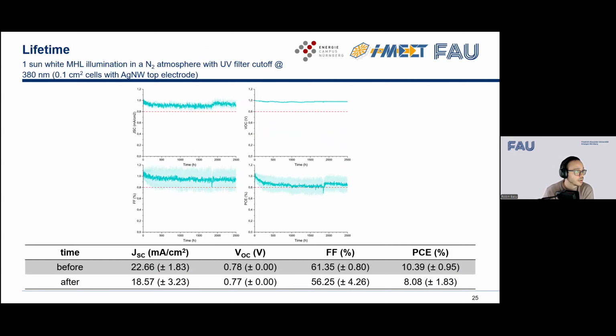Okay, and of course, what about devices if they're not stable? So I put some cells in this case. This is 0.1 square centimeter cells with a silver nanowire top electrode underneath the metal halide lamp with a UV filter attached. So it's close to application degradation. And as you can see, the devices look very stable even after 2,500 hours.